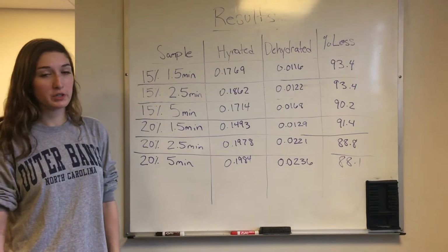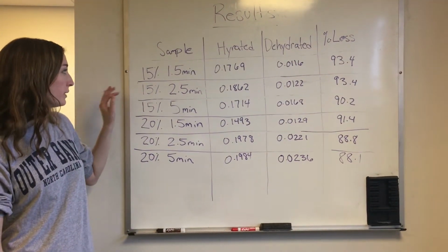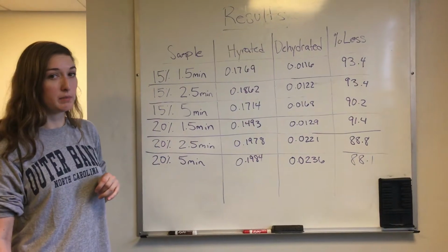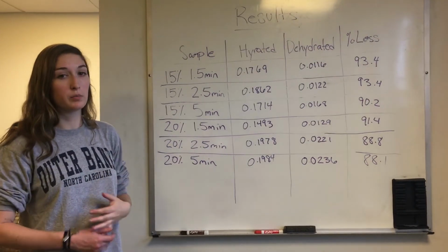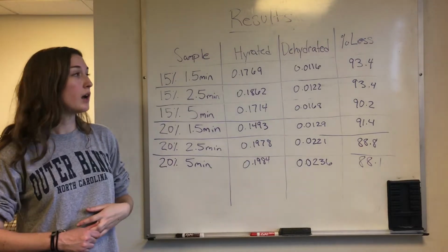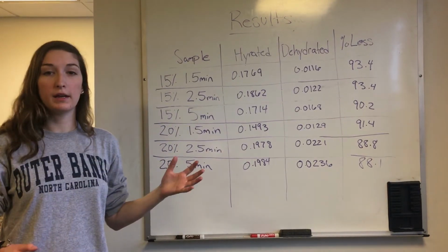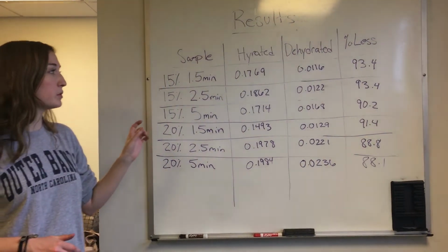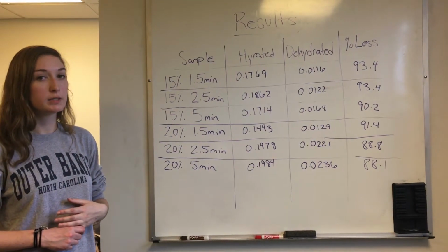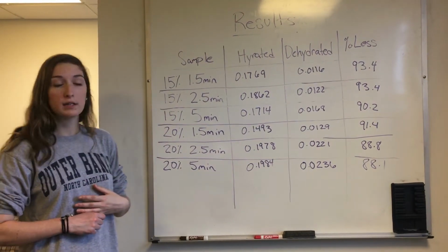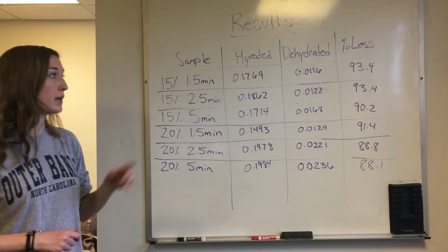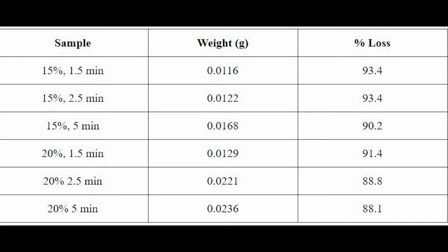In order to perform our hydrogel swell test, we took 6 samples, 3 of 15% PEG and 3 with 20% PEG, and we used different exposure times of 1.5 minutes, 2.5 minutes, and 5 minutes to test how they affected the cross-linking. Samples were hydrated in DI water for 24 hours, weighed, and then they were placed into a lyophilizer where they were dehydrated for 72 hours and then re-weighed. As you can see, the percent loss of water is listed here. And this was used to figure out the cross-linking density. The highest cross-linking density was determined at 5-minute UV exposure for 15% and 5-minute for 20%.